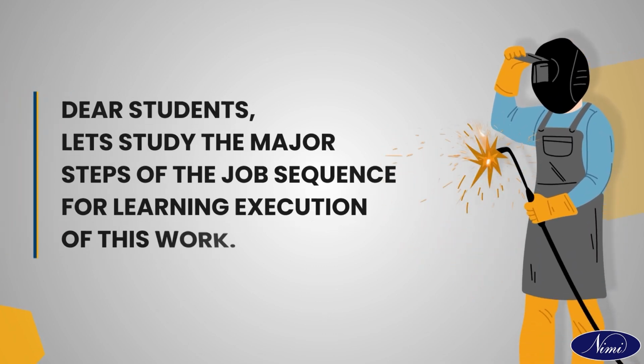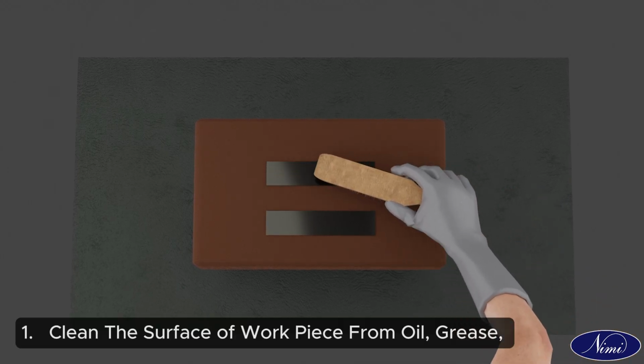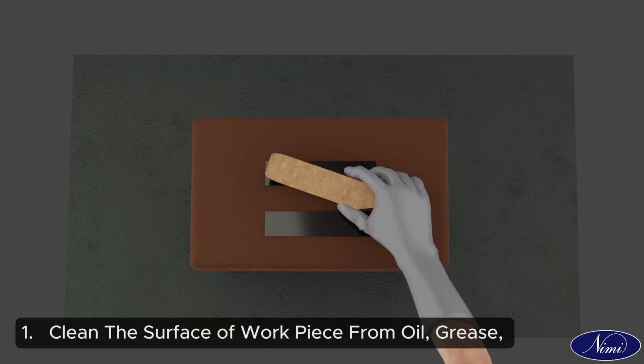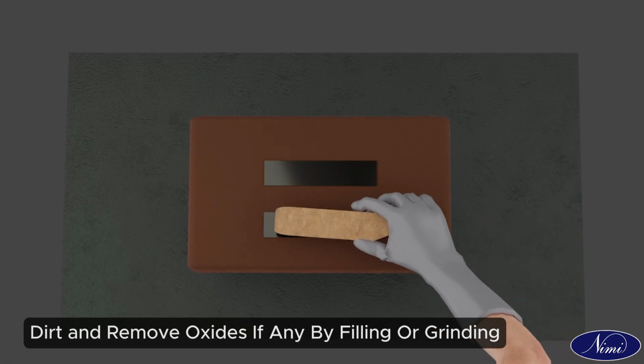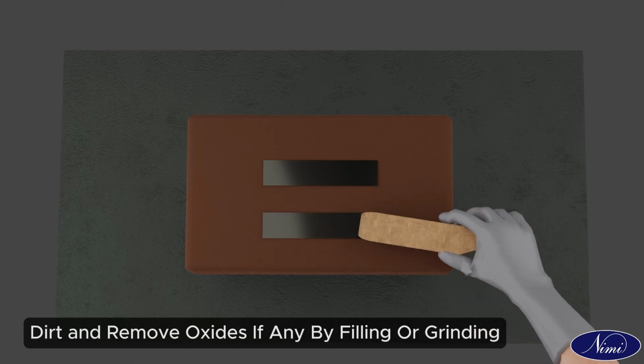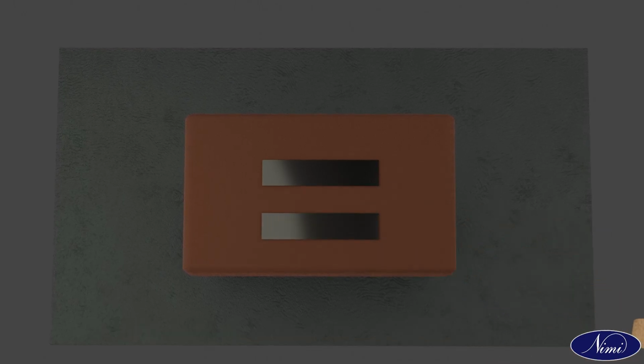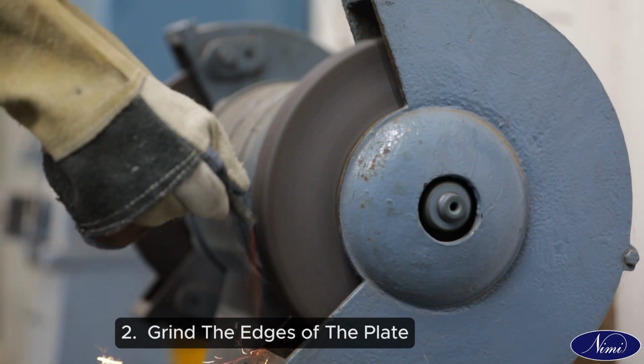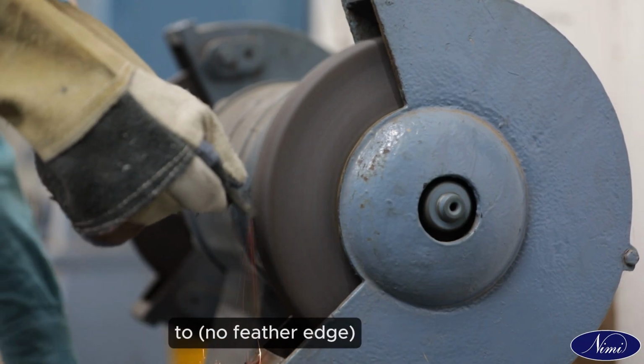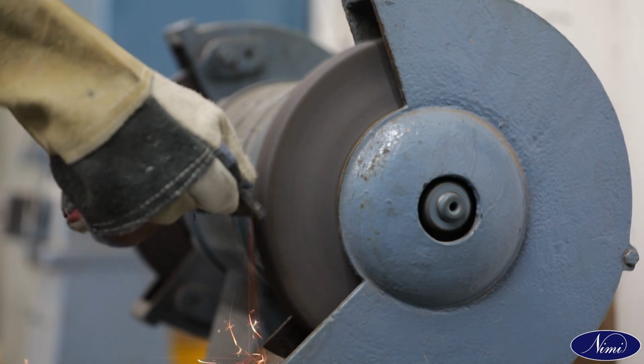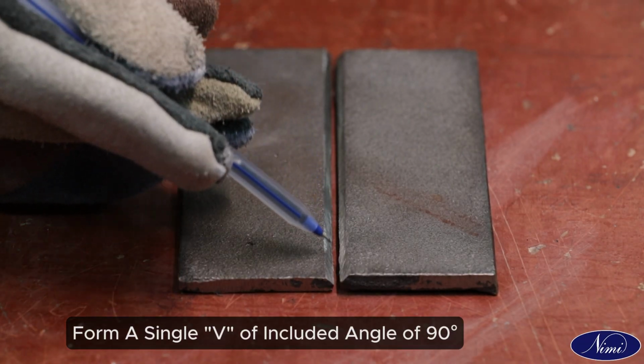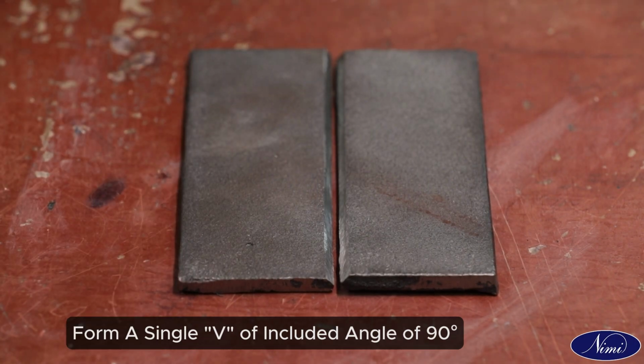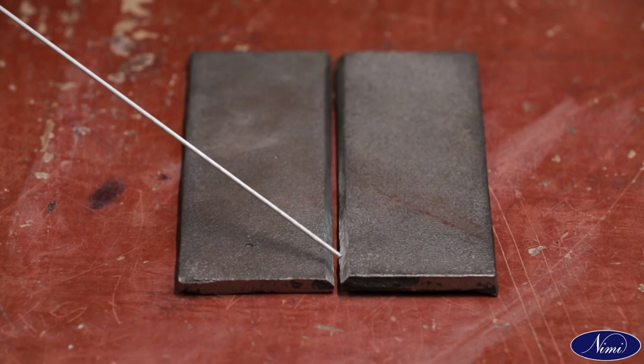Dear students, let's study the major steps of the job sequence for learning execution of this work. 1. Clean the surface of the workpiece from oil, grease, dirt, and remove oxides if any by filing or grinding. 2. Grind the edges of the plate to no feather edges. Form a single V of included angle of 90 degrees. Round off all sharp edges.